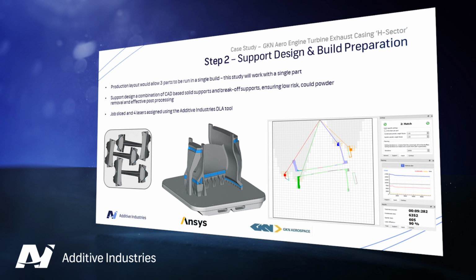So the support design uses a relatively conventional approach for metal AM components. We're using a combination of some solid CAD-based supports, some solid connections to the base plate to resist stress and thermal distortion, and also some break-off support structures, which in this case we generated using the Magics tool. These support structures allow certain features to be hand-dressed and subsequently cleaned up for the finished component. These also take into account things like powder removal, powder extraction, and also low risk to the build process.